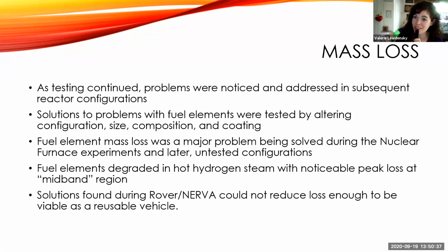The problem is that because of this hydrogen, because of how high temperature it is and how volatile that hydrogen can be, it actually ate away at this matrix. And so they noticed this substantial mass loss. And that is not only a problem because this is nuclear material, but it also means that our reusable model of this is completely limited. To have to replace the fuel elements kind of defeats the purpose in many ways.